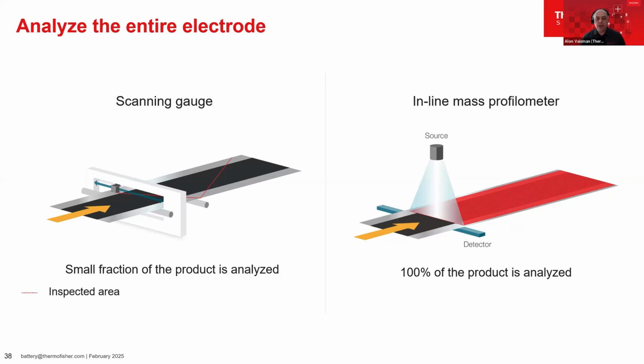For example, if the line speed is 60 meters per minute and the sensor takes 5 seconds to move left to right, 5 meters of product would have passed until one single profile measurement is completed by the scanning gauge. Areas that do not pass under the sensor are not analyzed at all, and the coating variations or defects could easily be missed.